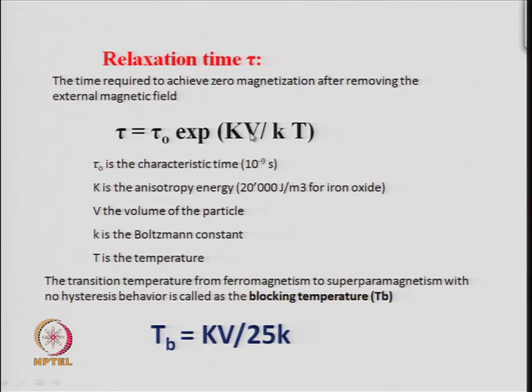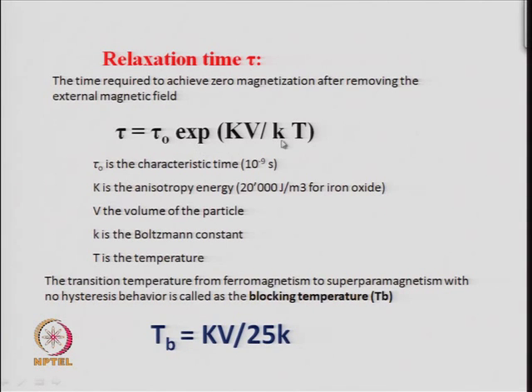So, that means, smaller the volume, smaller will be the relaxation time, because it is exponentially related, and of course, higher the temperature, smaller will be the time. So, if you increase the temperature, it will relax faster. This is understandable, because you are increasing the thermal energy. So, kT is increasing, and kT is in the denominator of the exponential, and hence higher the value of T, lower will be the relaxation time, it will relax faster.